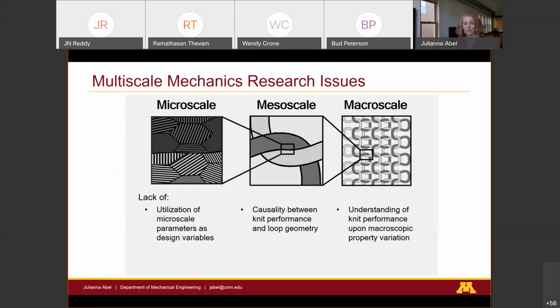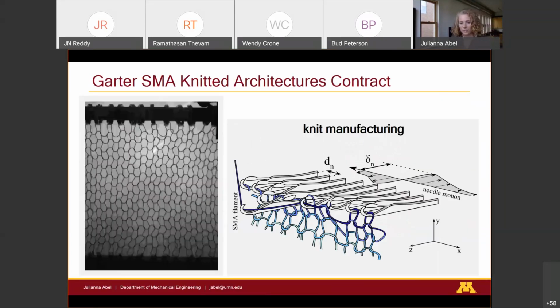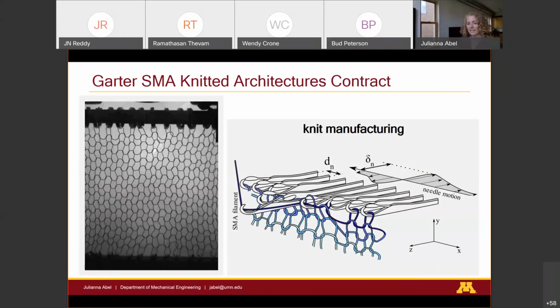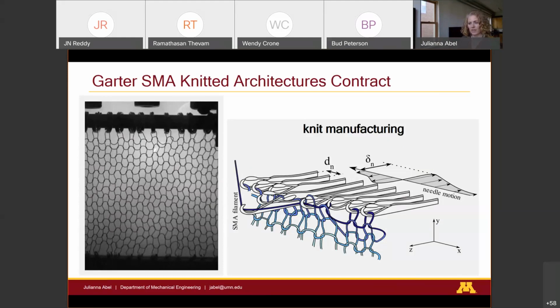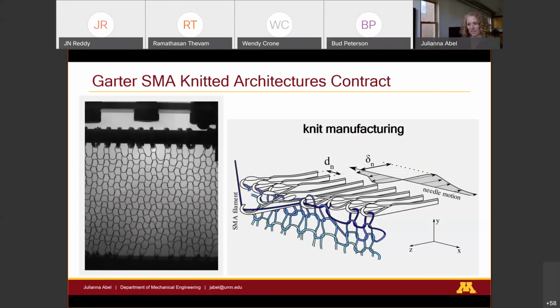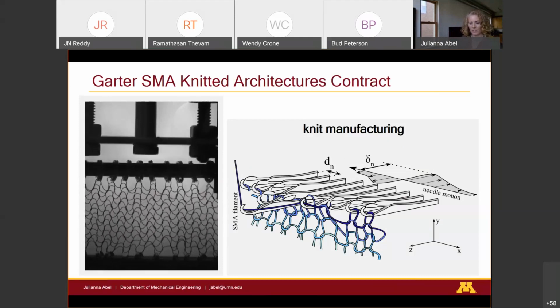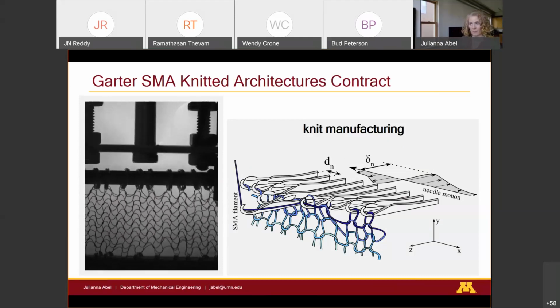So we're going to start up here at the macro scale because it is the easiest to conceptualize. Knitted structures, like I said, are interlacing loops of adjacent unit cells, pulled through one another on a knitting machine that you see on your right. Depending on how far apart those needles are spaced and how far they pull them back, you get different loop sizes. And this is a simple garter knit. So it's going to provide in-plane contraction like you saw in the previous example. And so we're getting about 50% in-plane contraction distributed over a surface.